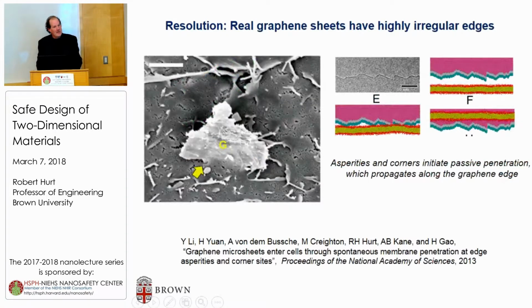But it turns out that the resolution has to do with the structure of graphene sheets. These graphene flakes don't look like the pictures on the cover of Science magazine. They've been ripped, essentially, by exfoliation processes from the lattice. And look how irregular their surfaces are. If you take an irregular surface and you dip that into a membrane, then you concentrate the force at these tips, it readily penetrates, and once it does, it propagates along the membrane, and you can get passive uptake associated with the irregular shape of the surfaces in graphene nanoflakes. And it's a bit like cutting bread. If you try to cut a piece of bread with a smooth knife, and the bread were flat and you pushed on it, it'd be very hard to break the crust. But they make bread knives serrated for a good reason, to concentrate the force on tips.